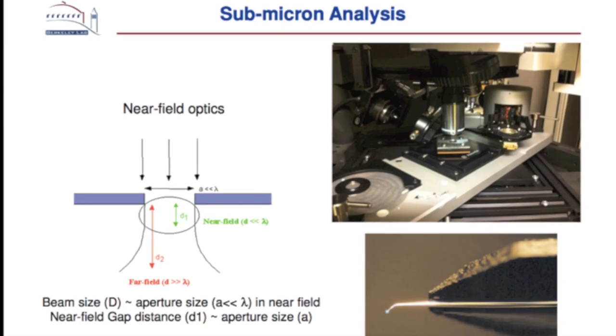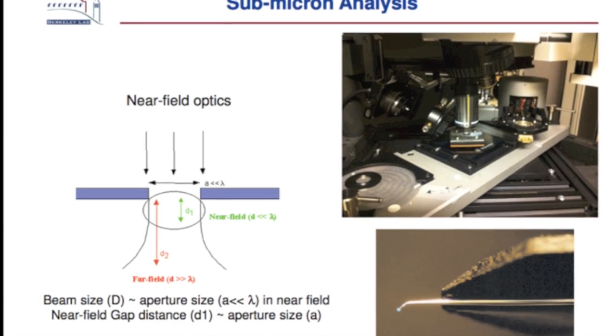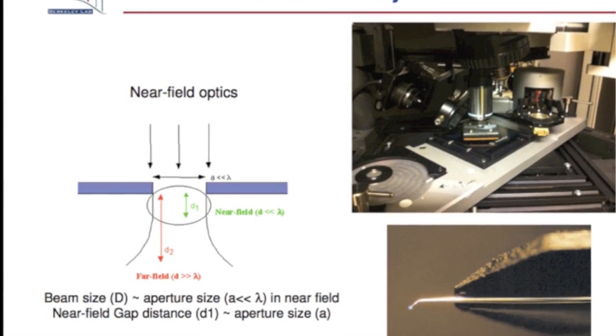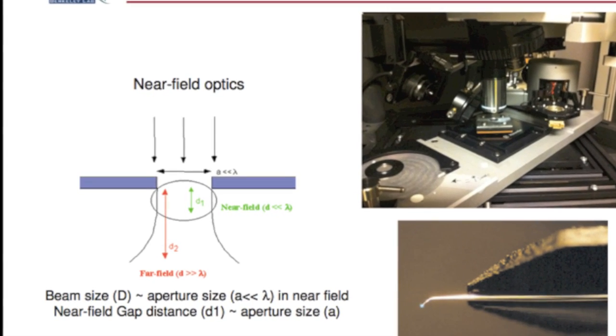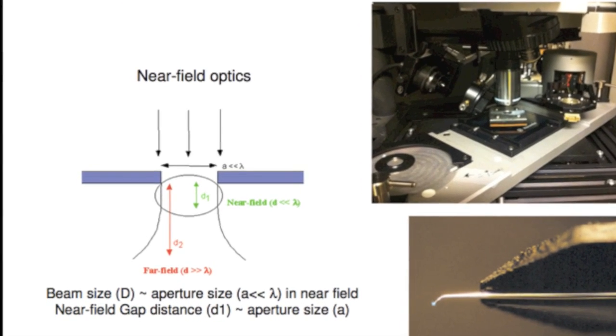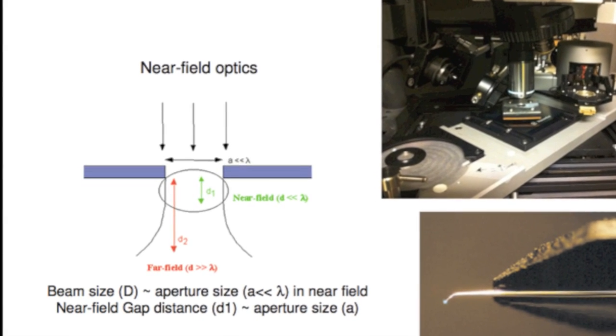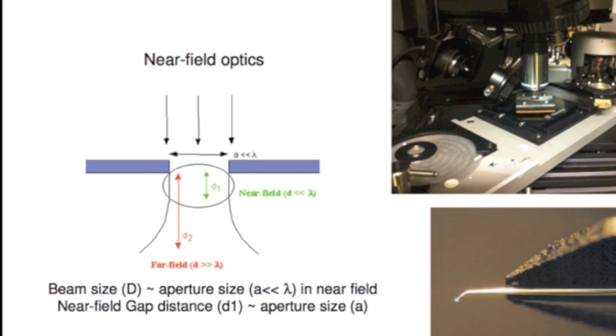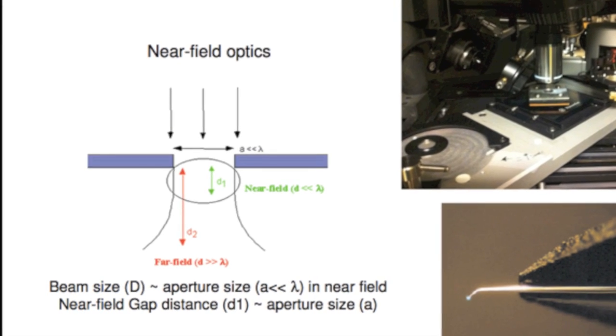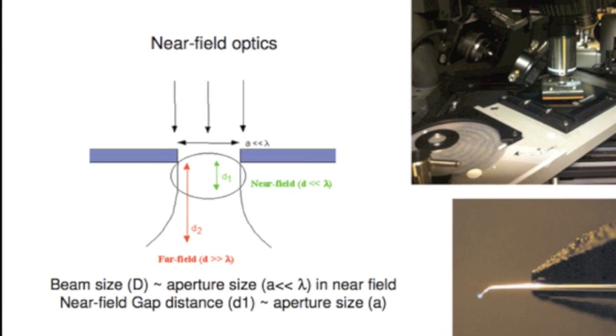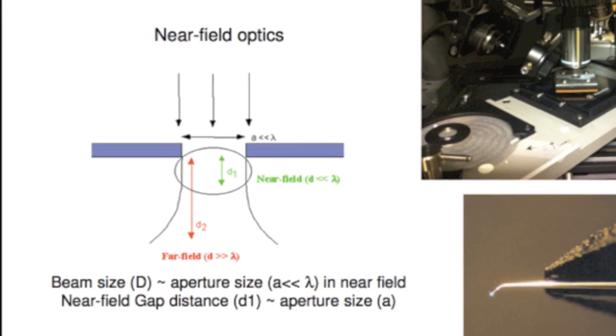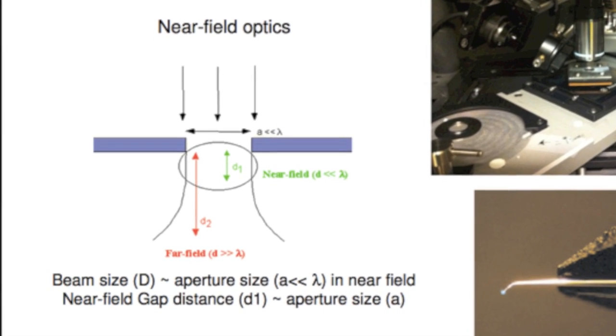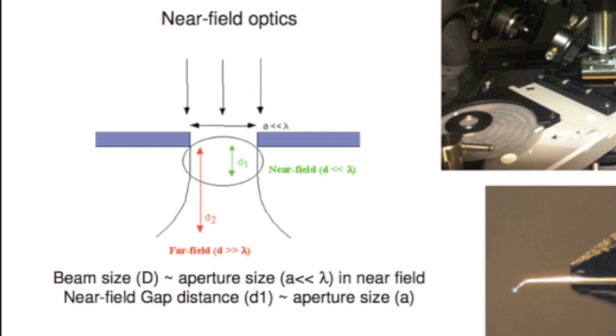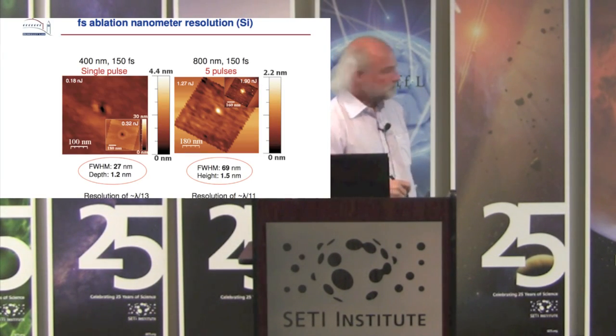So there's a whole field of science called near field optics. If I take a fiber, and I draw the fiber down to tens of nanometers, hundreds of nanometers, and I send a laser beam through that fiber, and I place that fiber within the near field, which means much less than the wavelength, the distance from the end of my aperture to my sample is on the order of nanometers, and my aperture is nanometers, I can do laser ablation, I can do LIBS down at those scales, okay? So this is a way of beating the diffraction limit.